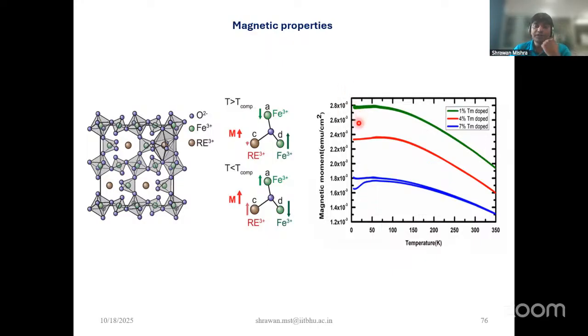So here you can see that there are some wiggles appearing. And when we go to 7%, when thulium is in a larger proportion, you can clearly see a bifurcation in this blue curve at low temperature. That's a compensation point, and after this the spin glass behavior can be realized, but we are not pretty sure because we haven't performed experiments in that direction. But a future measurement could clarify whether this bifurcation is the formation of a spin glass, or what the reason could be.